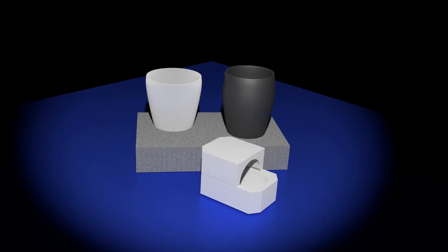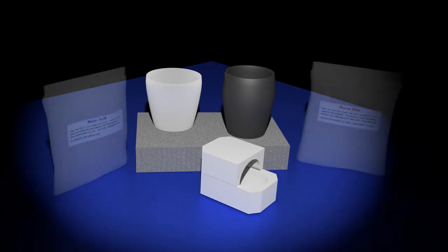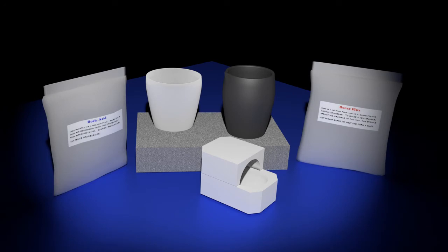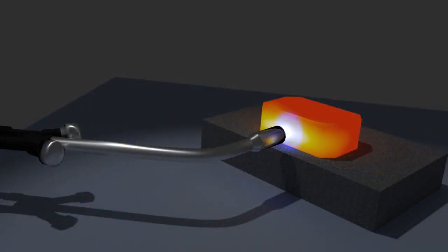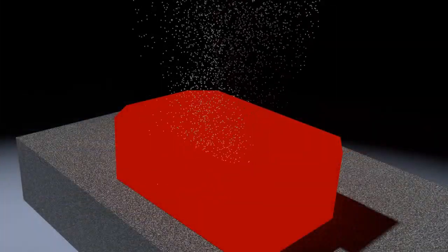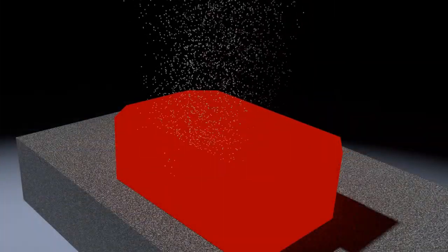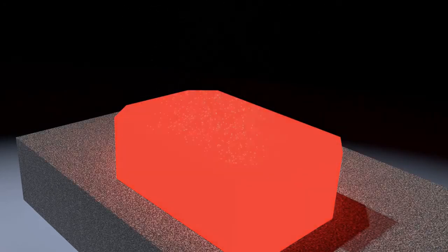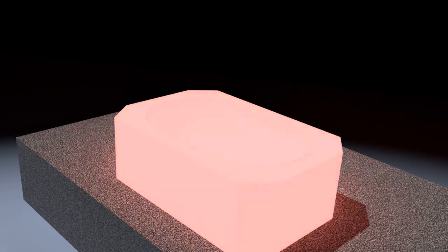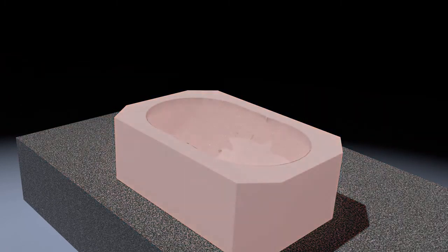Preparing your crucible: select either an unused crucible or one that has only been used to melt refined gold. When using a fresh crucible, you must first flux it, sealing its pores, thus preventing it from absorbing gold. Heat your crucible to red hot. Sprinkle flux on the inside of the crucible. A mixture of 50 percent borax and 50 percent boric acid is the most commonly used flux. The flux will melt rapidly, forming a thin glaze and sealing the crucible's pores.